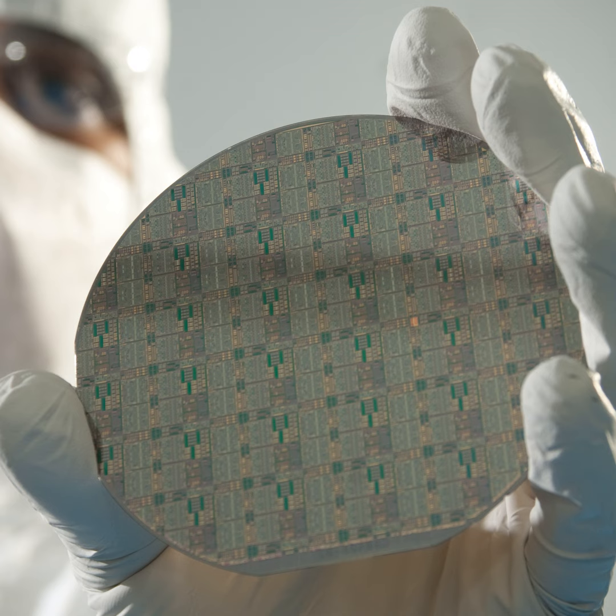So what DARPA is doing, and we absolutely support it, is investing in ways to address that heat bottleneck in GaN through some new innovations. And the innovations are really all about how do I get the heat out of the GaN as fast as possible. And when we do that, we can now go back in and really generate more heat. So it's a self-licking ice cream cone. For example, if today's GaN output power is 5 watts per millimeter, and the transistor is 50% efficient, that means it's also generating 5 watts per millimeter of heat, and that millimeter is the size of the device. So through innovations in material selection, substrates, etc., we can get the heat out quicker and get higher power density.